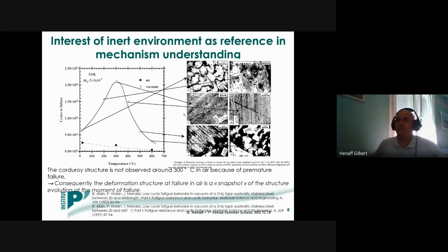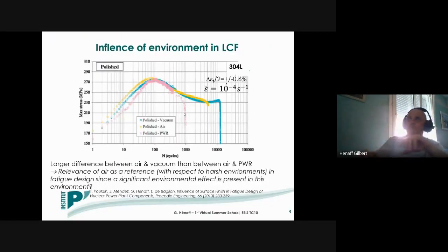And this is very important to keep in mind the fact that what you observed in air is just a moment during the fatigue life. So again, here an example about low cycle fatigue of austenitic stainless steel, in that case, a 304L steel. And here we compare the fatigue response in 3 different environments, namely vacuum, considered as an inert environment, ambient air, and a PWR, pressurized water reactor environment, which is the actual operating condition in nuclear power plants, especially in